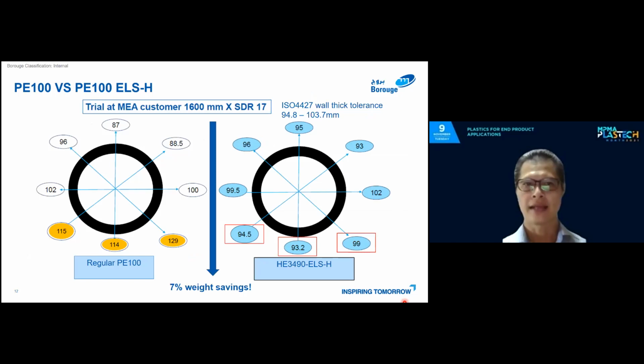Here is a trial that was done in the Middle East, and this size is 1600 mm, SDR 17. According to ISO 4427, the wall thickness tolerance will be around 94.8 to 103.7 mm. With the standard PE100, after extrusion, you can see the wall thickness at 4 to 7 o'clock is already outside the tolerance prescribed in ISO 4427, more than 103.7 mm.